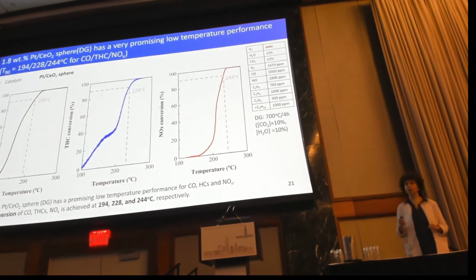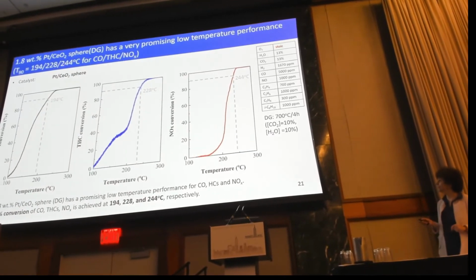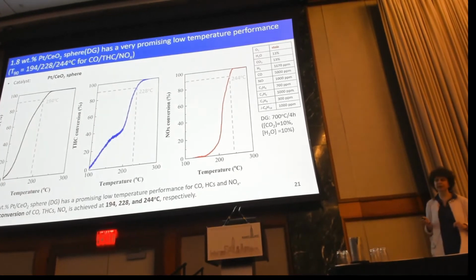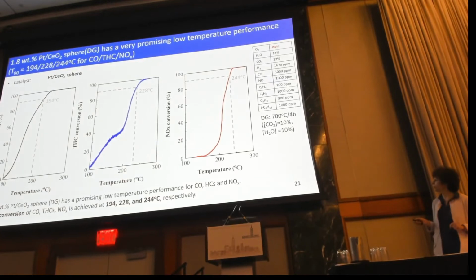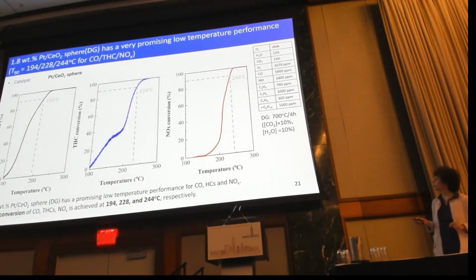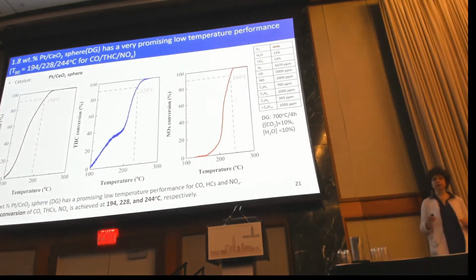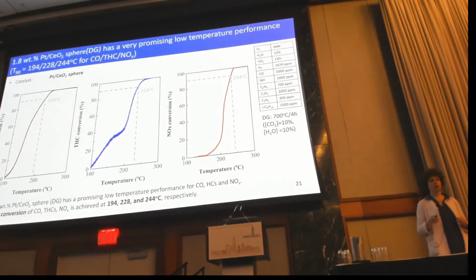Okay, so let me show you how the platinum ceria sphere catalyst performs after degreening. Here you see the CO conversion, total hydrocarbon conversion, and NOx conversion as a function of temperature. Again, T90 is achieved at 194 degrees C for CO. For total hydrocarbons, T90 is achieved at 228, and in this case we also see NOx conversion, which obviously we didn't see in the first part of the talk. We see that T90, 90% conversion of NOx, is at 244 degrees C. Okay, so this is without zirconium.